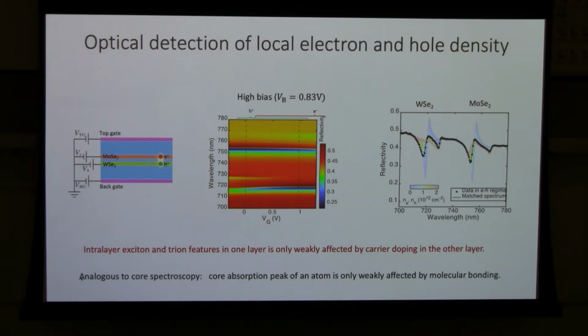The answer, somewhat hand-wavingly, is that we can make an analogy to core level spectroscopy with X-rays. The intralayer exciton and the trions are really tightly bound, so they are probing behavior at the nanometer scale or relatively high energy. As a result, they're not so sensitive to whether there is another hole in the adjacent layer. Similar to the X-ray core level transition for atoms, they are very element specific. When bound to other atoms in a molecule, it only leads to a very small change.